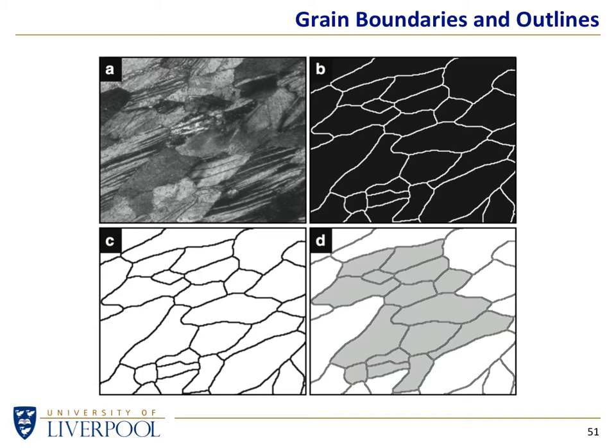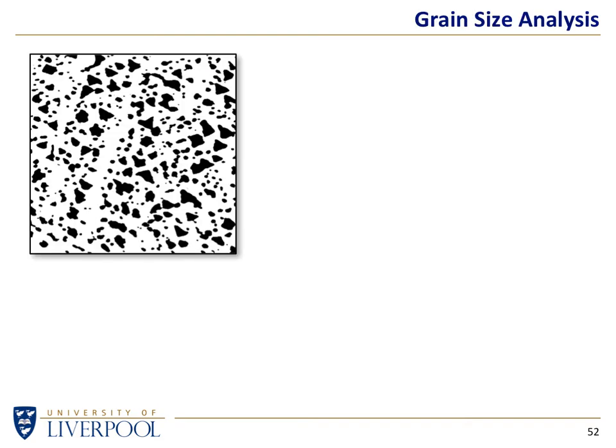When it comes to working out what shape they are, we can't rely on the shape of any of these grains that's touching the edge, because, for instance, in this case, we've got no idea if the rest of the grain finishes in a sort of circular manner or is a very elongated grain. So any grain that's touching the edge, we effectively have to throw away, but the ones that are wholly within the image, we can look at those and figure out, is there a preferential orientation to these particular grains? What shape are they? What size are they? What's the size distribution, and are they oriented in a particular way, which gives us a clue as to the formation of this particular system.